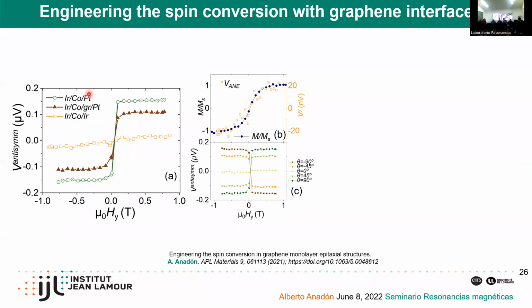So at first, just by looking at the voltage that we obtain when we sweep the magnetic field with a thermal gradient in our sample, we already observed that graphene is reducing significantly the voltage that we have. And so this is a first measurement. So we need to compute how big is the anomalous Nernst effect in the system to subtract it and to really estimate what's the effect of graphene in the system.